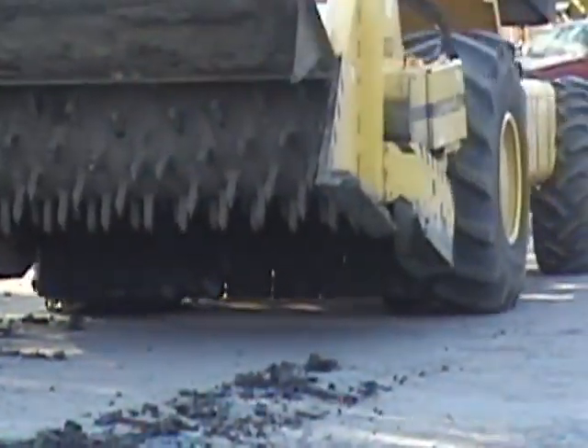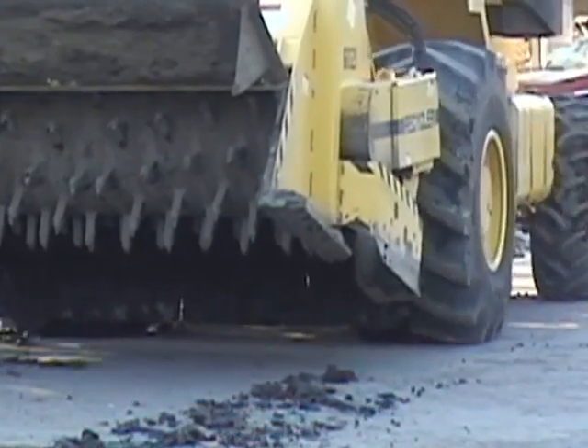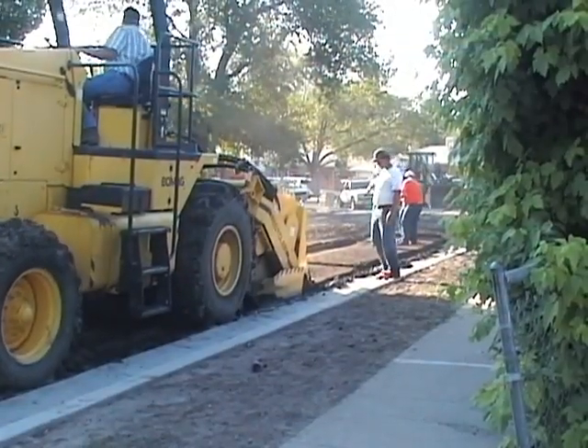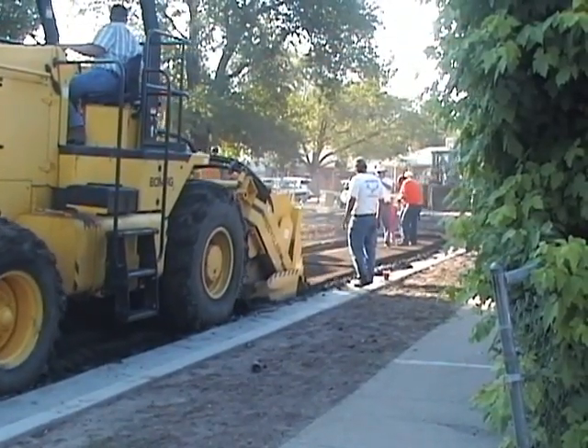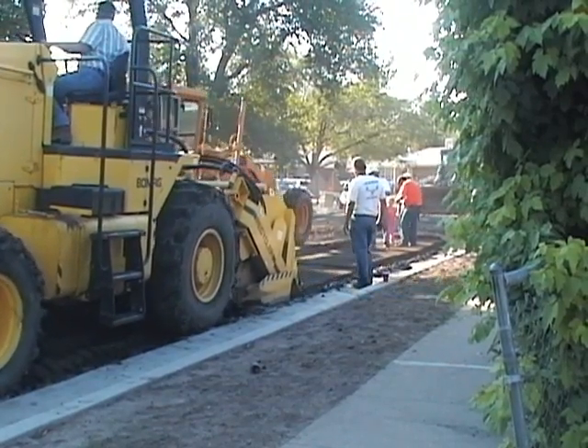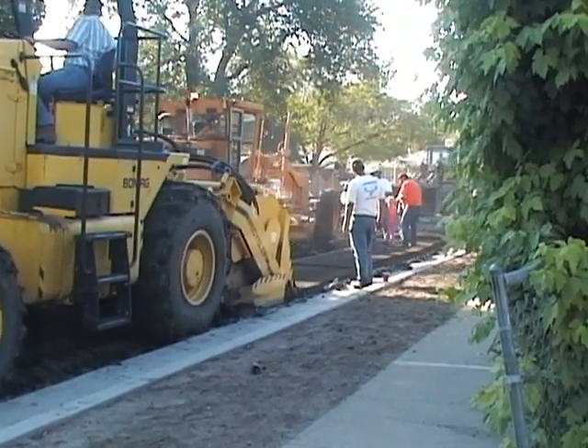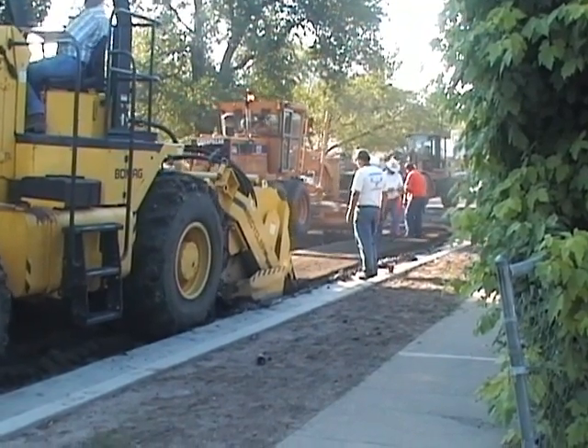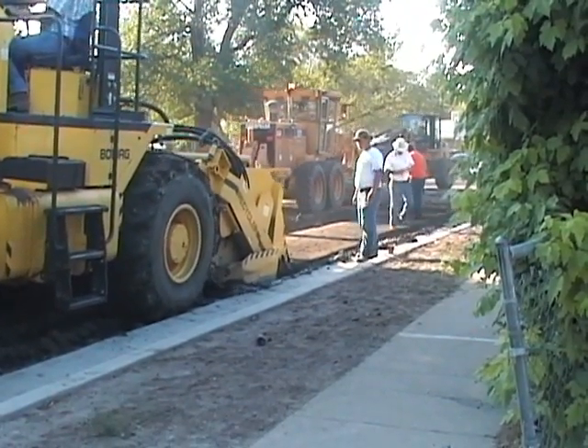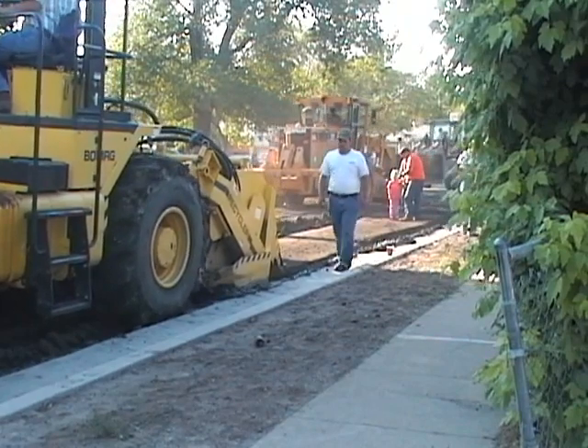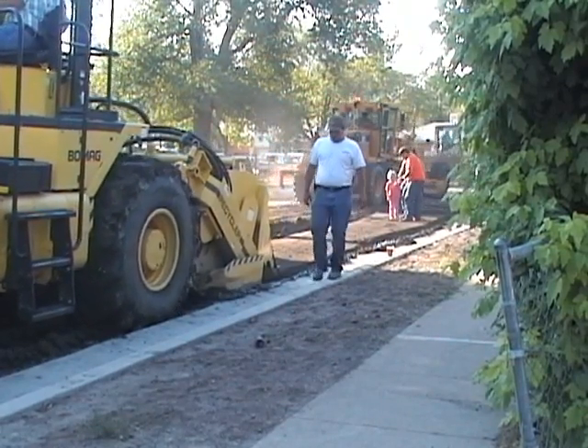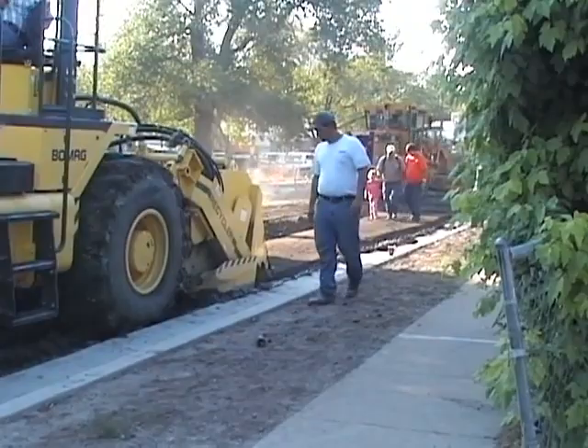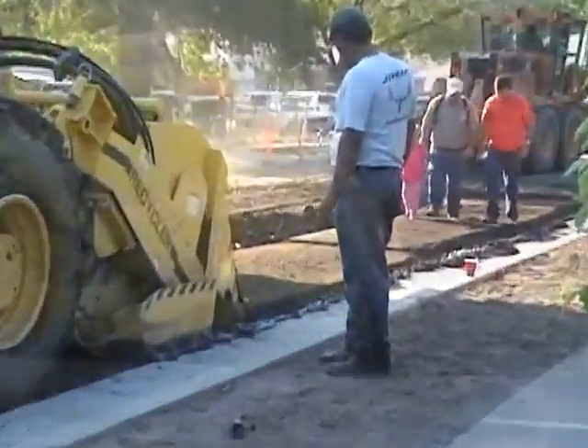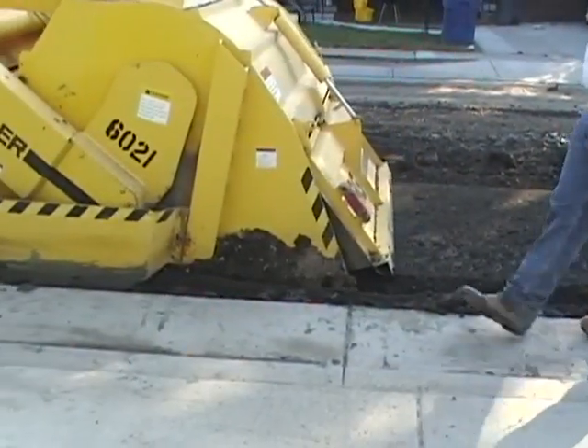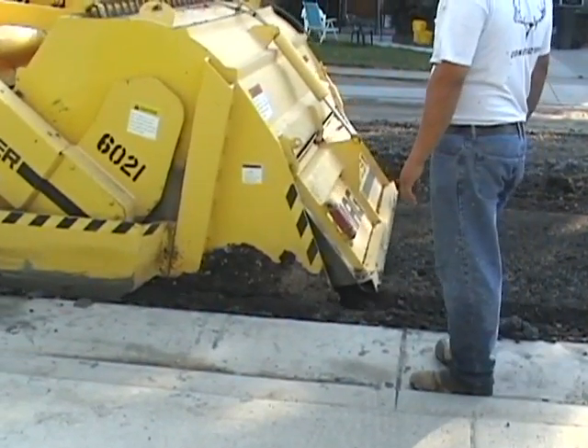The cement slurry was mixed into the base course using a pulverizer. The pulverizer made one pass down the road, and an 8-ton vibratory roller passed behind the pulverizer to compact the freshly mixed CTB. On the day of CTB reconstruction, the air temperature reached 102 degrees Fahrenheit, the wind speed was insignificant, and the relative humidity was around 10%. Previous BYU research indicates that in those conditions, use of a set retarder, as applied on this project, is warranted.